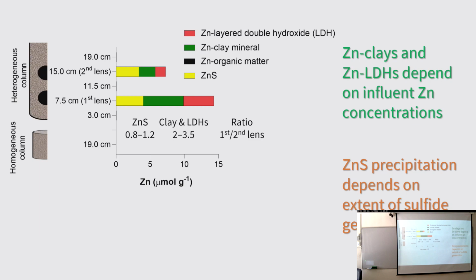Now that implies that we have different retention mechanisms, or different forces that are controlling these retention mechanisms. For the clays and layered double hydroxides, it appears that their formation is mainly dependent on the concentration of zinc in the incoming groundwater. However, for the zinc sulfide, it appears that there is a different force controlling this rate of accumulation, most likely the rate of sulfide production, which is dependent on the activity of the sulfate-reducing bacteria.